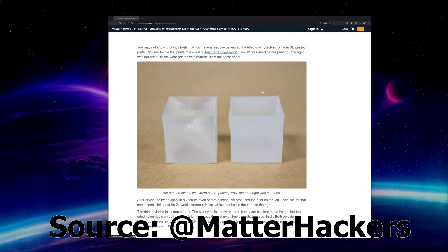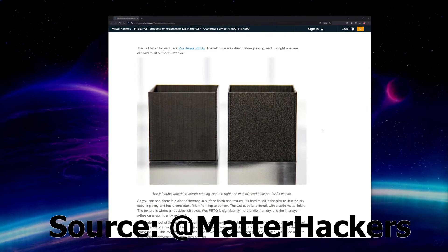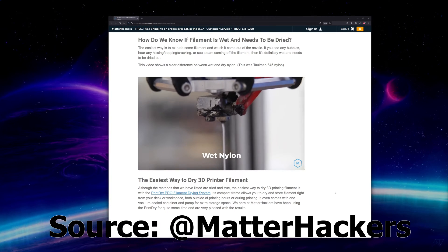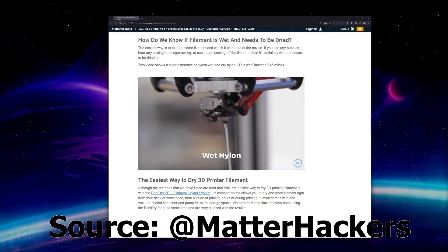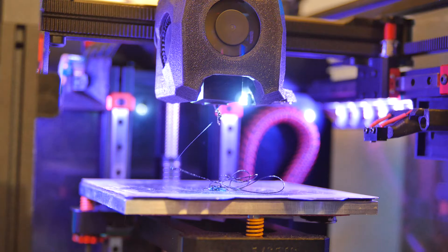But is this really necessary, and what does moisture ingress into our filament actually do? Mostly you'll notice poor cosmetic results — things like increased stringing and a rough, inconsistent-looking extrusion. One key symptom of moist filament is a snap, crackle, pop sort of sound audible from the nozzle during extrusion. You might also notice some steam coming from the nozzle.